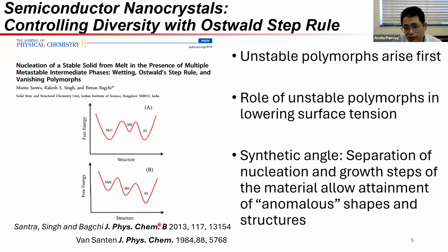Now, the idea of the Ostwald step rule is mainly that unstable polymorphs seem to arise first out of a melt before the eventual material arises. And this has prominent effects for how nucleation proceeds, which is excellently described in both of these works, and how wetting occurs. For a clever synthetic chemist, there's one more dimension to this, because you have all these other associated metastable phases. These would vanish in bulk. These would not actually be ever isolated correctly in bulk, but rather they do exist, and they are important.